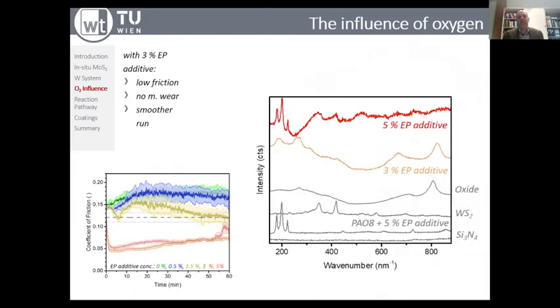When we look a little bit more deeply into the details, again, the comparison of the Raman spectra for the silicon nitride, so the ceramic counterbody, the PAO8 with the additives on board, the WS2 spectra. Also for the tungsten trioxide, we can clearly see that if you increase the concentration of EP additive from 3% to 5%, you step by step start building up the characteristic peaks of the tungsten disulfide. You can also, for the 3% EP additive, clearly see the peak of the oxide, of the tungsten trioxide.